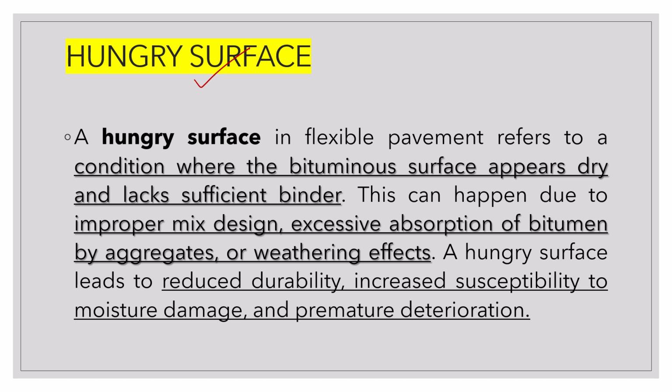bituminous surface. This condition occurs mainly due to dry binder, or if the binder quantity is not sufficient, or sufficient binder is not there in the mix. This type of failure, hungry surface failure, can occur. This can be due to improper mix design, if the aggregate absorbs excess bitumen, or the aggregate has higher absorption capacity, and due to weathering effects.